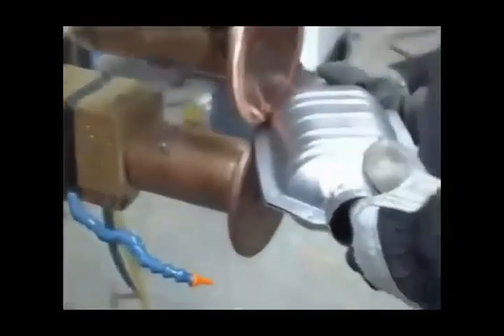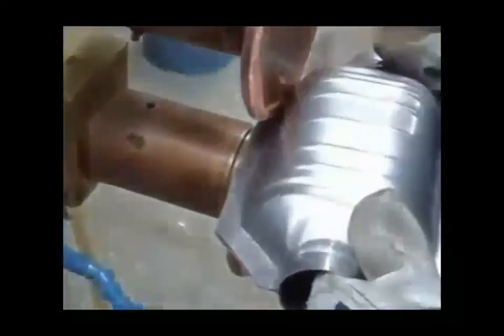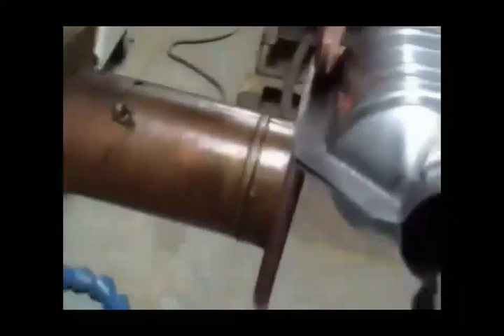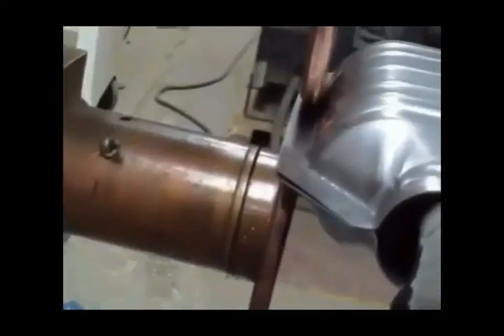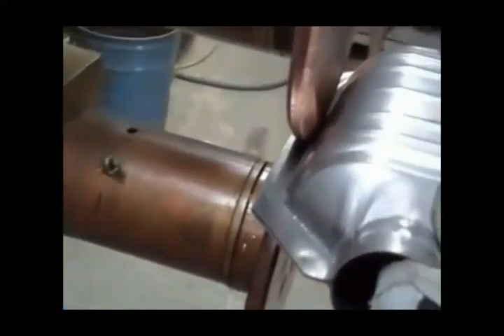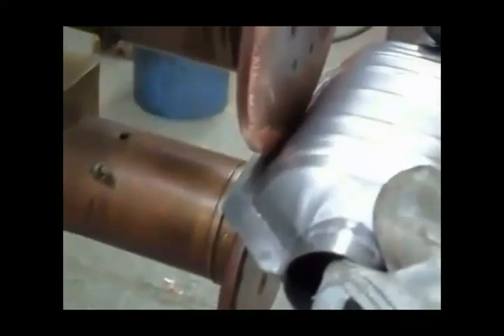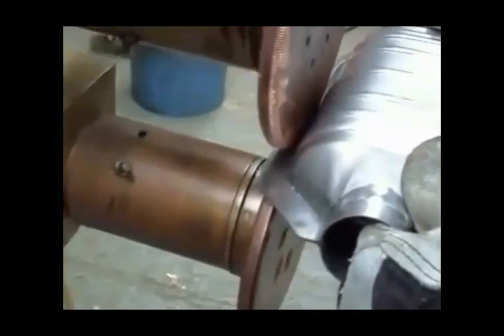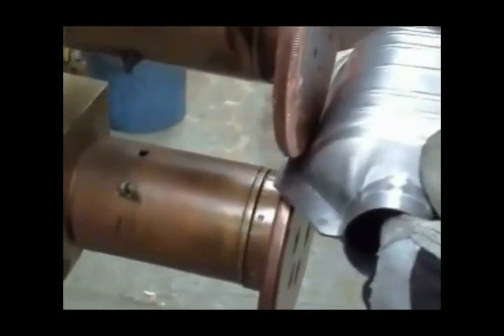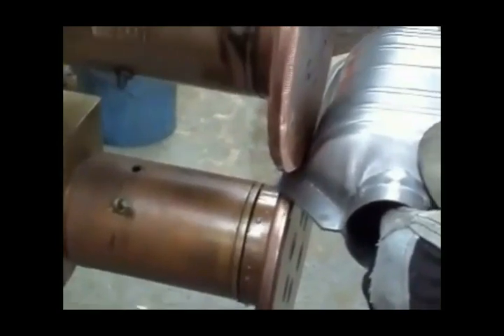The muffler is made out of zinc-coated steel. The evaporation temperature of zinc is 907 degrees Celsius. Since there is no smoke coming out of the faying surface during welding, this muffler must be welded below 907 degrees Celsius.